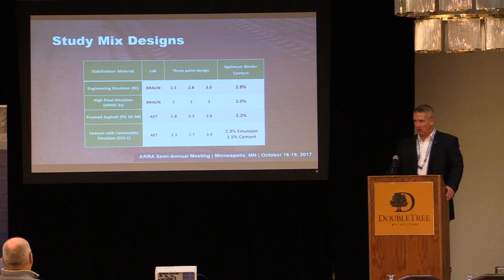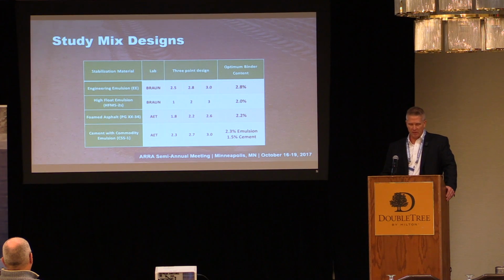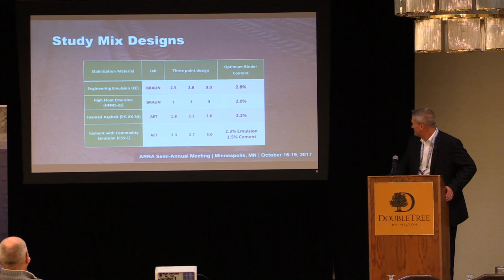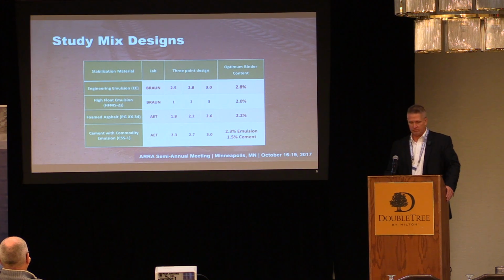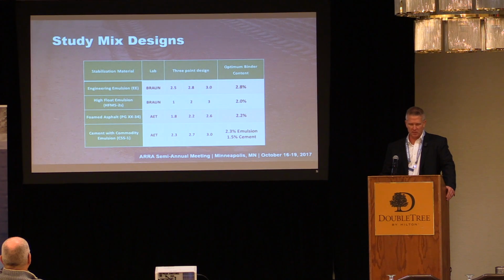As you can see here, they were all three-point designs, and the optimum binder content was determined with that three-point design, and is shown here on the right. 2.8 for engineered emulsion, 2.0 for high float emulsion, 2.2 for foamed asphalt, and 2.3% emulsion and 1.5% cement with the cement plus emulsion design.